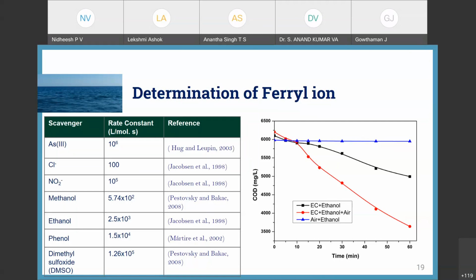Now instead of that, we tried with ethanol. Ethanol has a good reaction rate with ferryl ions, around 2.5 times 10 raised to 3 liters per mole per second. So we did 3 types of experiment: electrocoagulation with ethanol, aerated electrocoagulation of ethanol, and only aeration. And we checked the COD removal from the system.